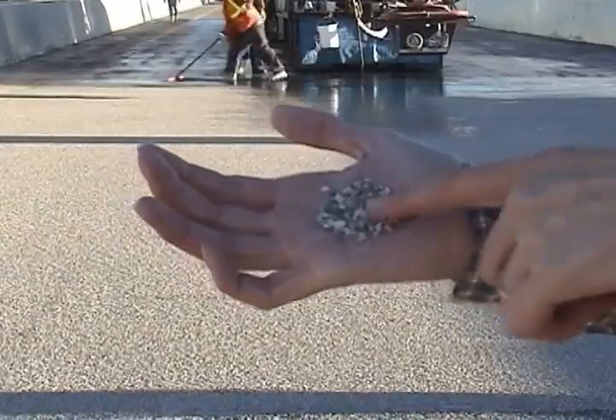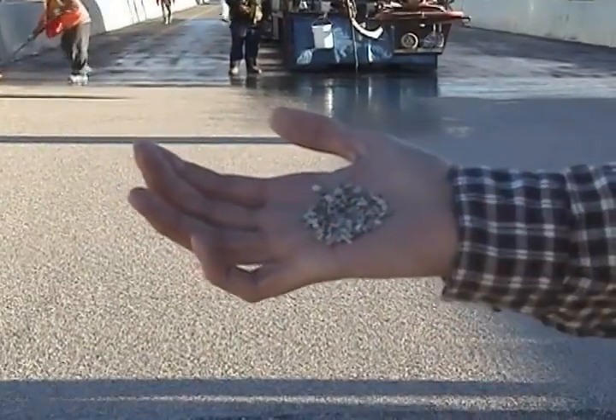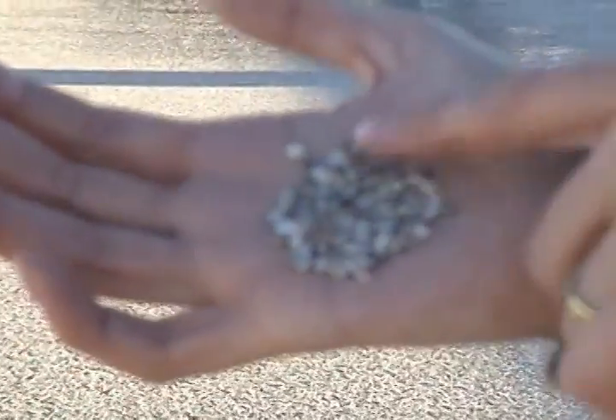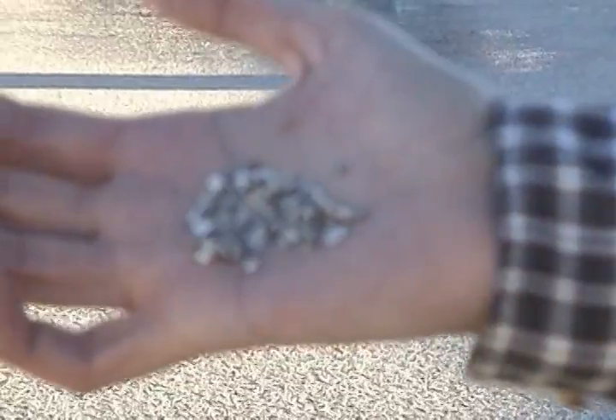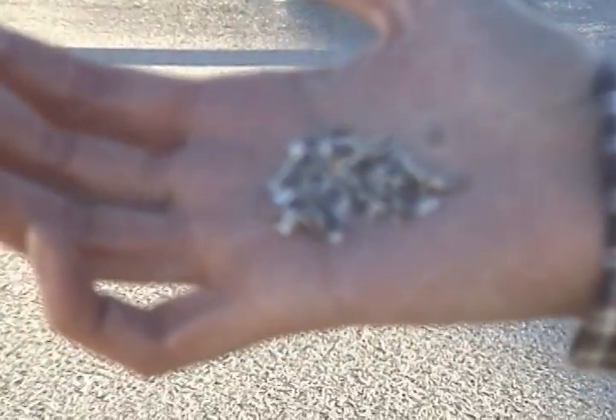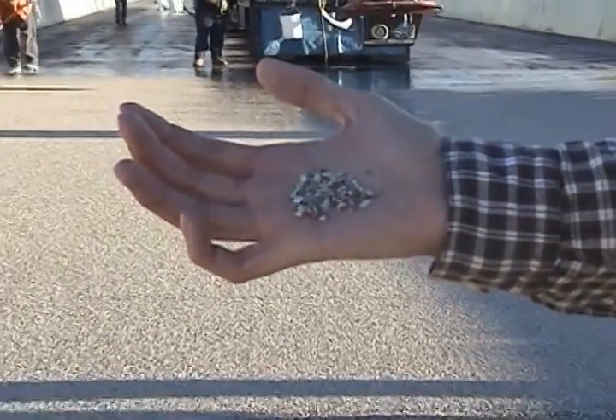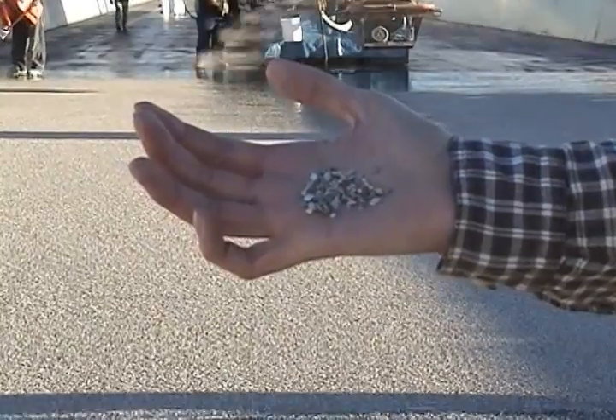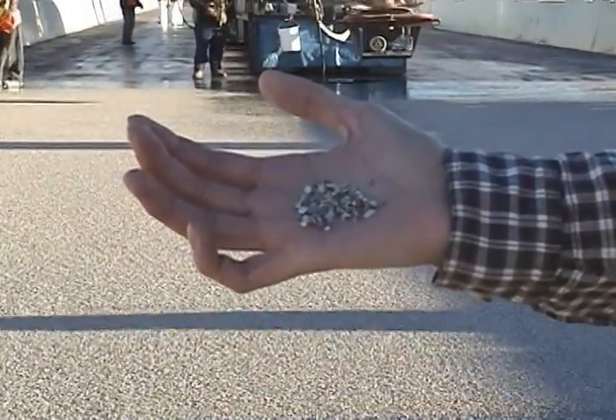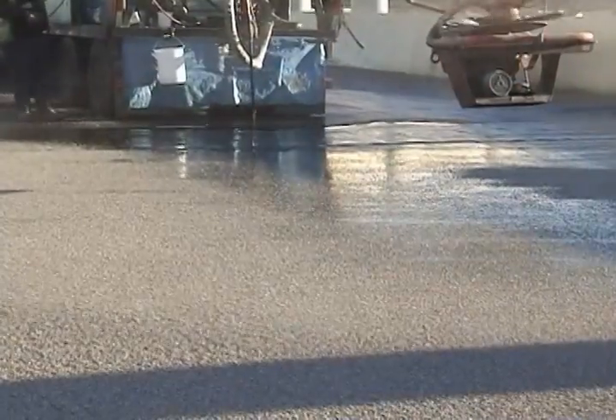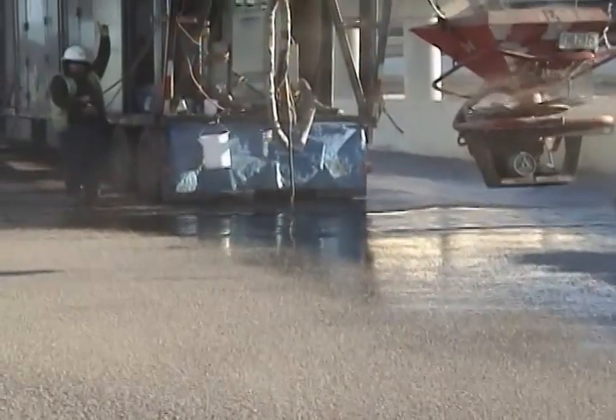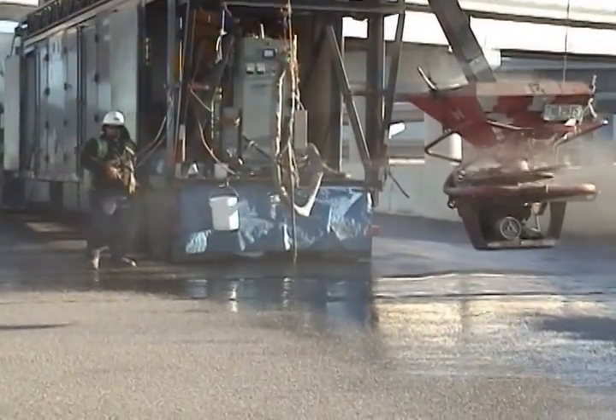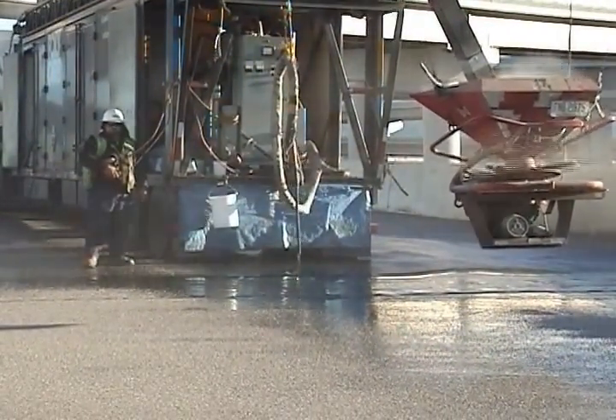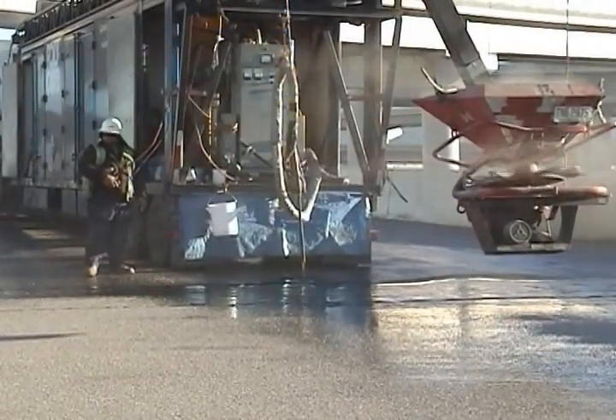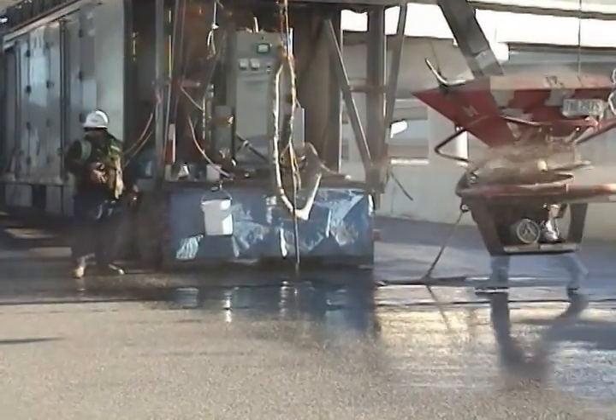The Flexogrid is automatically mixed in the polycarb trailer and dispensed onto the deck surface at about 100 degrees Fahrenheit. Heating the epoxy greatly increases the speed at which it will cure. Once the Flexogrid binder hits the deck, it is immediately spread onto the deck surface using squeegees and showered with aggregates. When this layer of epoxy and aggregates has hardened, the loose material is removed and a second layer of binder and aggregates is applied. The two layers combined will have a thickness of around 5/8 of an inch.